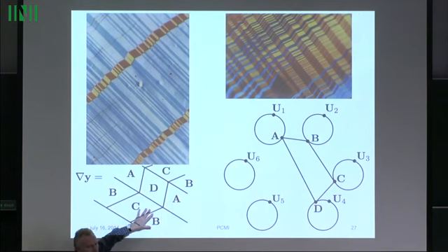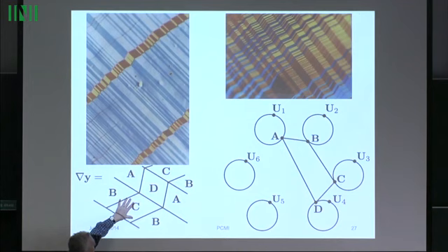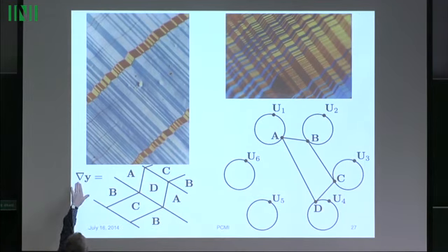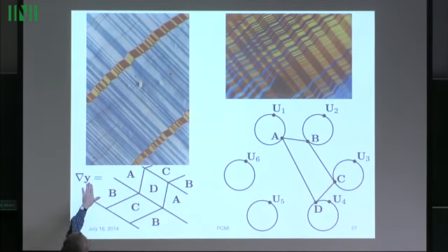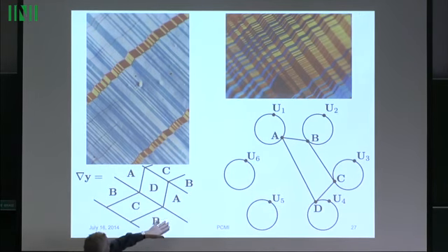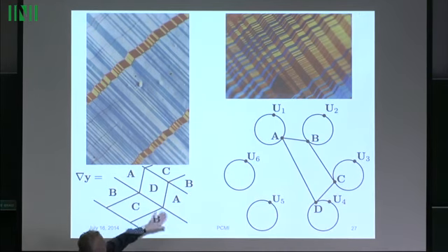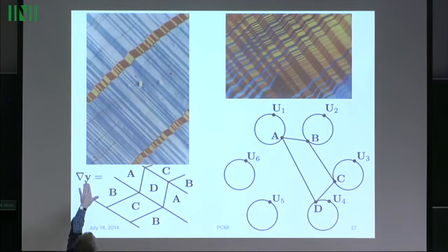This is a picture in the reference configuration. This is the domain omega. Now you take these deformations and you integrate up to find the function y. Then you take a polished, flat surface and you apply y to that flat surface. It will produce that picture, with all the surface relief. All the angles will agree perfectly with that picture. Even at the atomic level, the structure of the lattices will agree, back through the Cauchy-Born rule, with that picture. Okay? Good question.